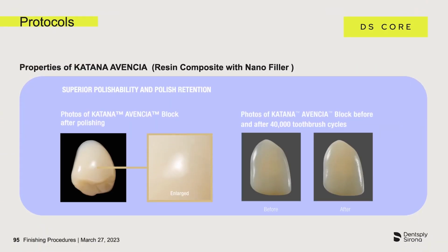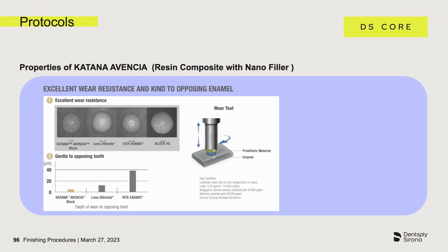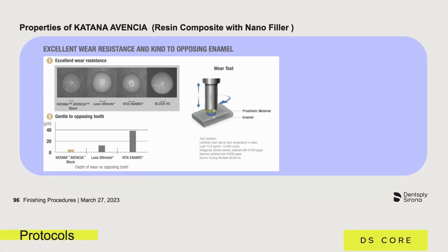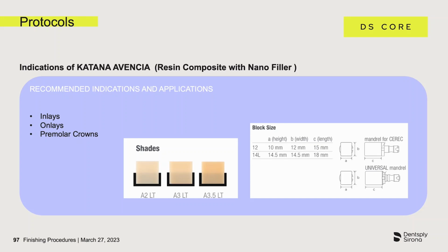One characteristic of Katana Avencia is its particularly good polishability, which is due to its structural composition. This polish is of high stability and long-term durability. Studies have shown that Katana Avencia is particularly wear resistant and kind to the opposing enamel. The indications for Katana Avencia are more likely to be inlays and possibly onlays and premolar crowns. Full crowns should be made in the anterior region and perhaps for premolars. There are stronger and more suitable materials for the posterior region.